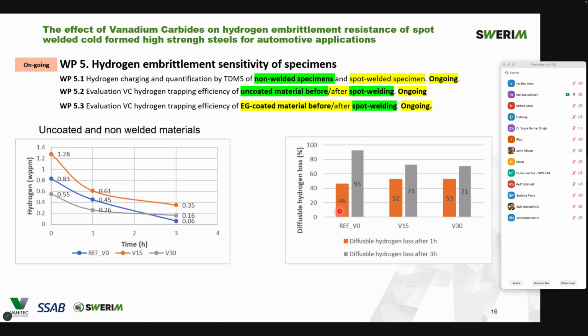The summary of this is on the graph on the right. To calculate that, we assumed that after charging, so after 0 hours, we had 100% hydrogen. Then we calculated how much was lost after 1 hour, that's the orange graph, which is quite similar for all of the materials, and how much was lost after 3 hours, the gray bars. Here we can see that the material with 0% vanadium lost the most, whereas the 0.15 and 0.30% material don't have a significant difference in hydrogen loss. That means they could retain more hydrogen compared to the reference material.